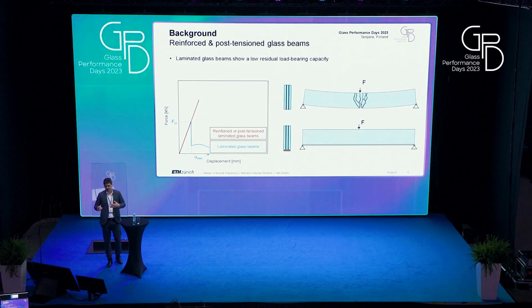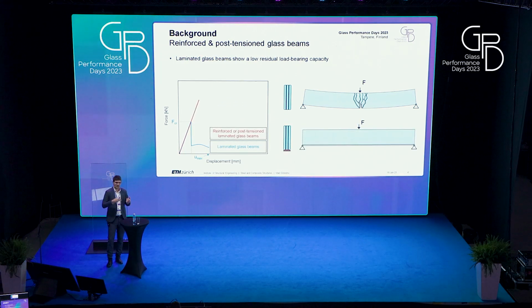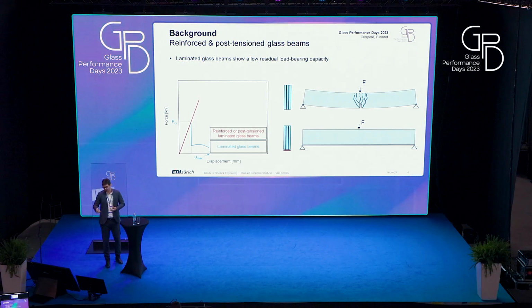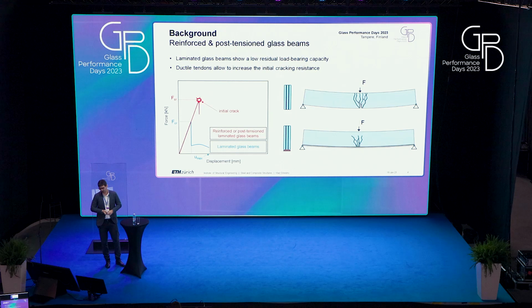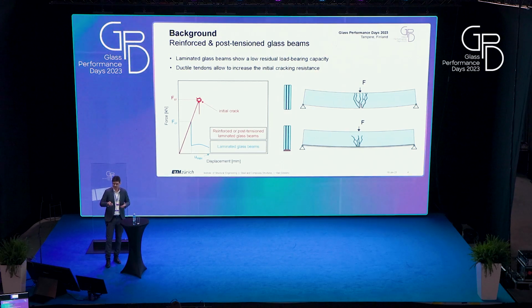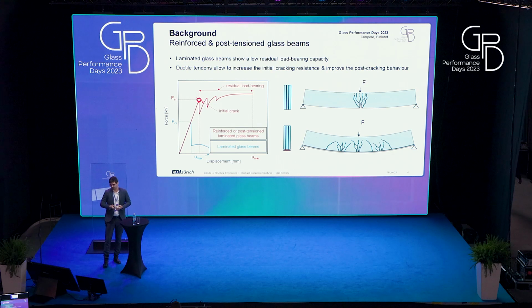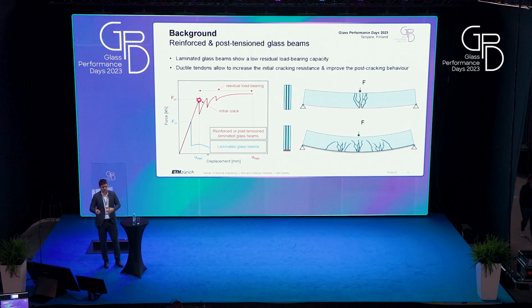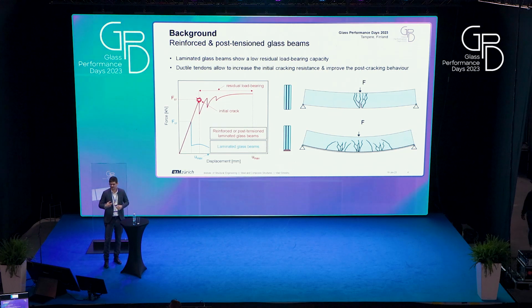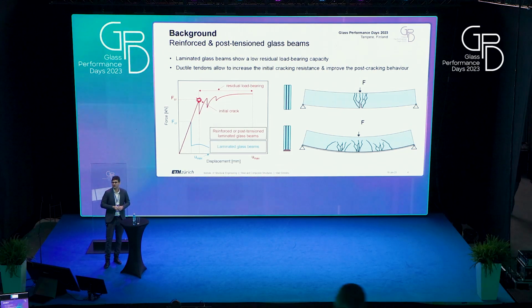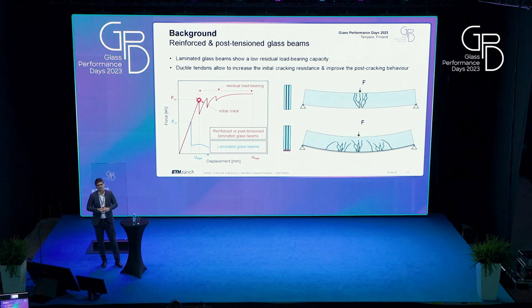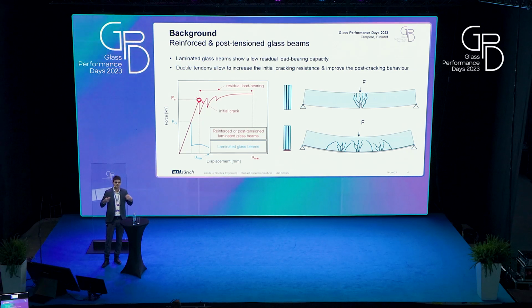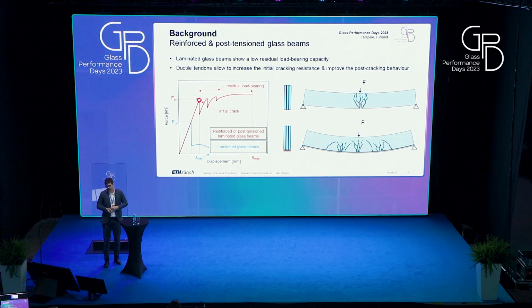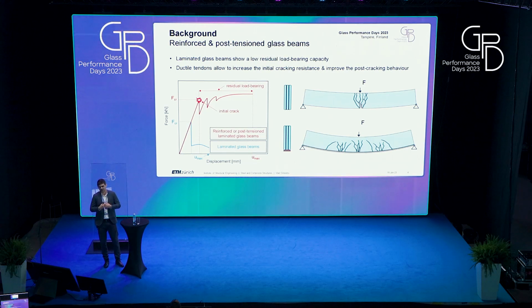Previous research tried to improve this behavior by adding a ductile tendon on the tension side. In this case, the initial cracking resistance can be increased, and furthermore the post-cracking behavior can be improved. However, if we look into real projects, these systems were not really applied a lot. There are, in my opinion, two reasons. One is that architects and clients usually want to see the free glass edge. The other reason is probably that, especially for post-tensioning, the approaches used are quite complex.